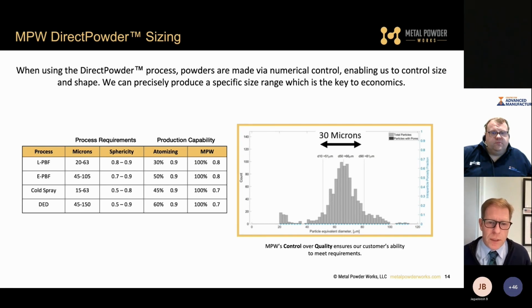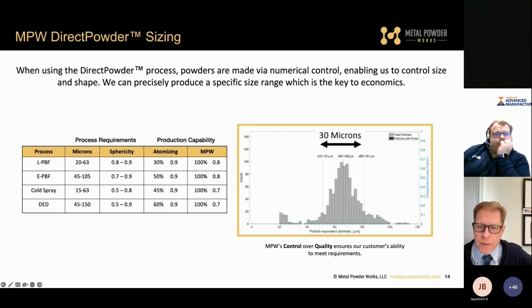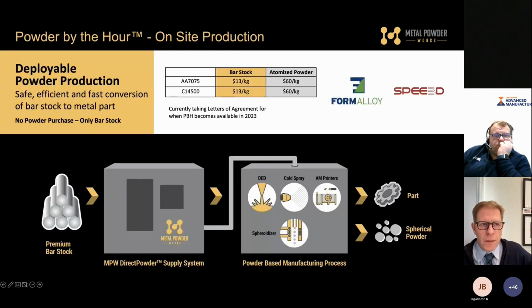Through our process, we can tailor the size and we get nearly 100% conversion efficiency. The sphericity we can match a little bit to the desired piece of the process. Our powder size distribution is nominally 30 microns, so we can take in a customer requirement, look at a D50, and then shift that up or down based on the requirement. So you can see where we get the size efficiency.